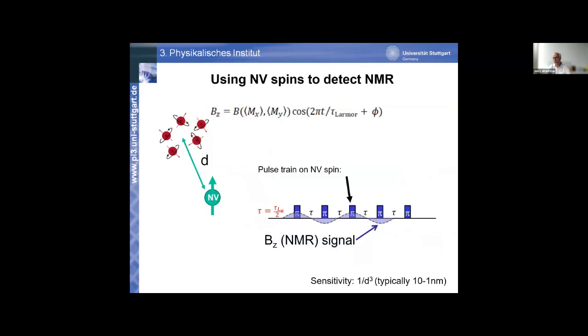All right. Nuclear magnetic spins have a magnetic moment which is roughly a factor of 1,000 smaller than electron spins. So being able to measure this would require a step ahead in sensitivity. And the sensitivity gain we bring about here comes from the fact that we are not measuring DC magnetic fields, but we generate a frequency selective magnetometer. The way we do this is described in this transparency.